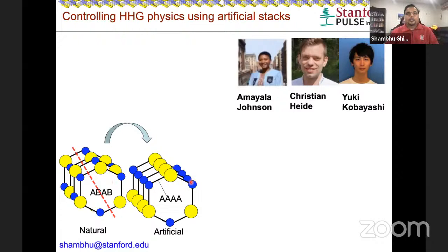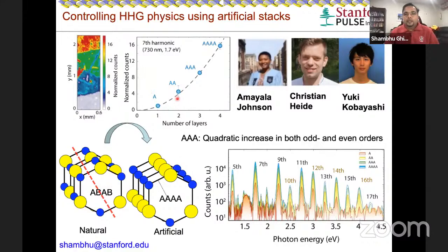So here, now we wanted to take the opportunity of this synthesis of materials, where we can stack these materials in different configurations, such as shown here. This is the AA stack. You basically take these layers out and rotate them and put them together in a way that all these atoms are lined up. And we look at the harmonics. First, this is the harmonic spectrum as a function of the number of layers put together in AA configuration, and you can see a nice increase of harmonic signal. The increasing harmonic signal is always nice. Now you can see the scaling. For example, the seventh-order harmonic scales quadratically pretty nicely as a function of the number of layers.